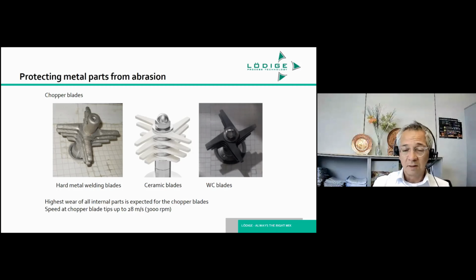But unfortunately, during operation, these items are subject to wear. In practical everyday operation, you don't always get to change or exchange these blades in a timely manner, because people operate 24/7 and production is not allowed to stop. So these blades get worn. Unfortunately, they wear, the coating disappears, and again, the metal comes to the surface and contaminates the mix. So this was not an ideal situation, because one could not take into account that operators would always change these blades in a timely manner.